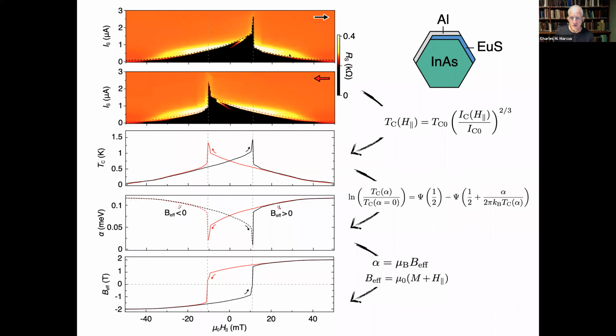In fact, you can do some theoretical analysis and go from the critical current and how that relates to the critical temperature through this 2/3 power, and infer, it wasn't measured, but inferred, an effective critical temperature that, as you see, has these spikes in it, the same spikes that you get from taking the critical current. The spikes I'm going to associate, if you haven't figured this out already, with the place where the magnetic field passes through its coercive field and has a zero. These are the zeros of the magnetic field where the europium sulfide becomes demagnetized.